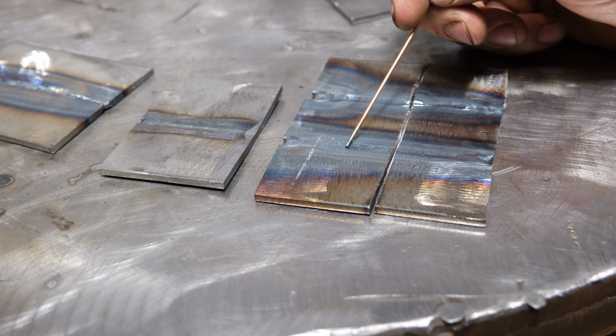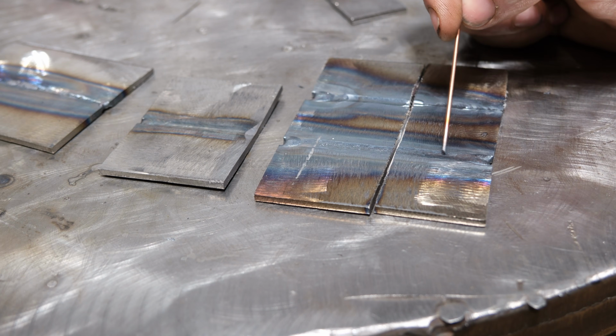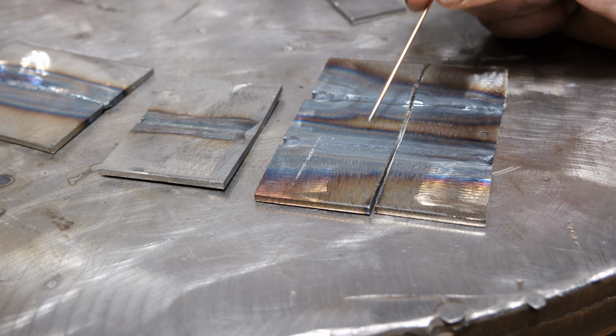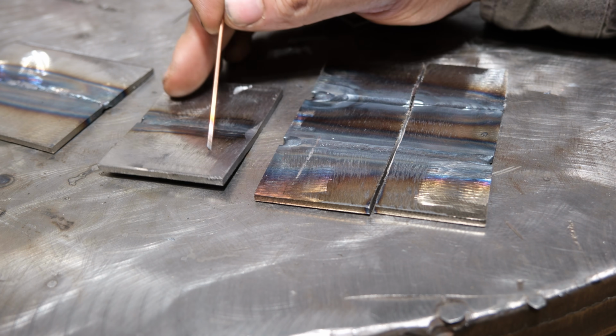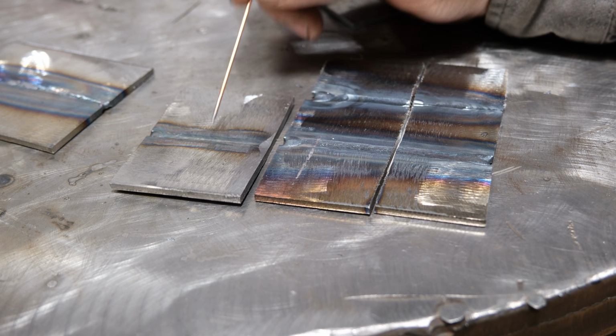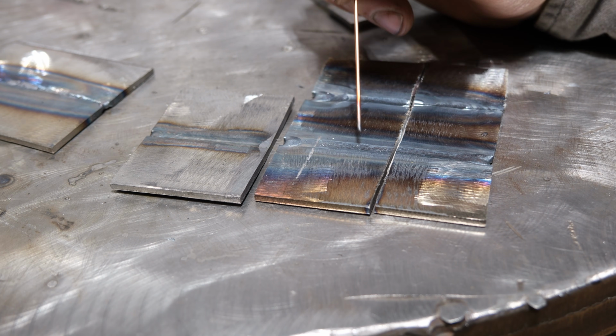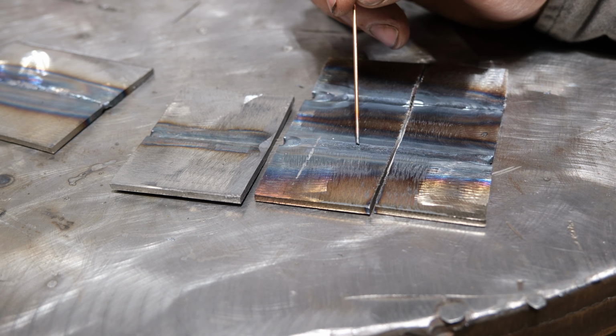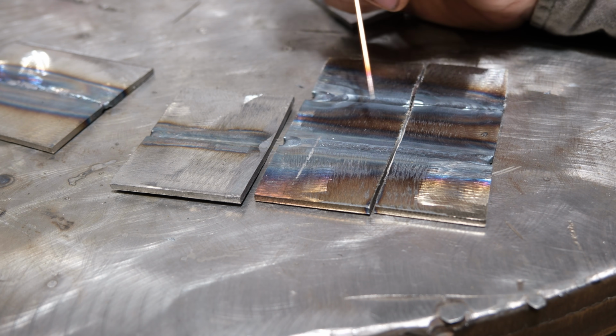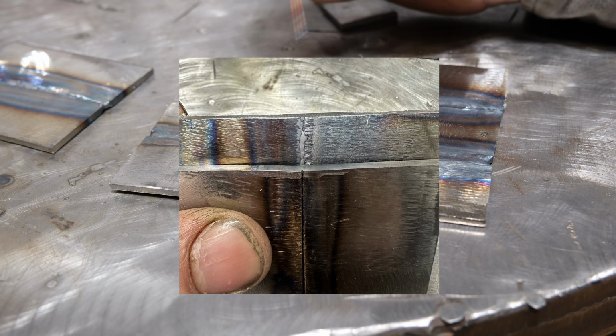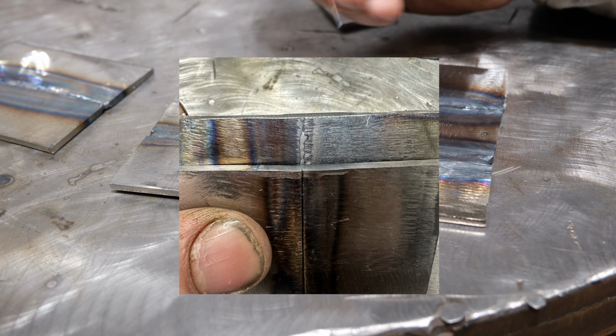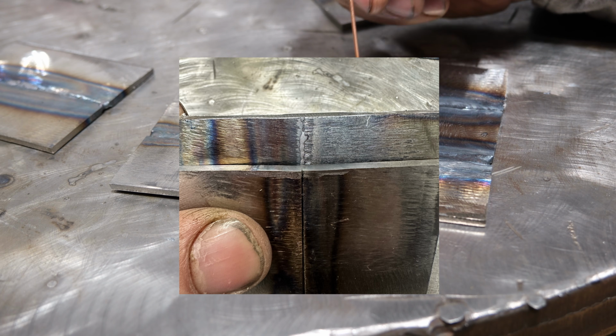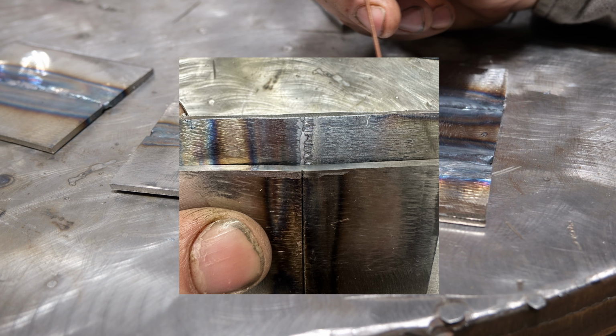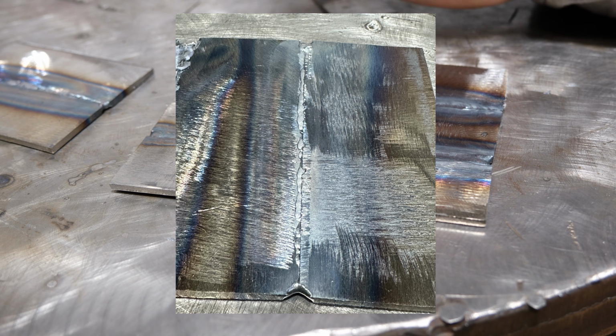So here is that fusion weld that you just saw the arc footage of, and you can tell just by the way this looks how high the heat input was because of my slow travel speed. When you compare it to this other fusion weld, it is a night and day difference. Therefore, the results are also night and day different. And I'll put pictures comparing these two up right now and talk about it. So what we're dealing with is we were able to almost fully weld 1/8 inch material via a fusion weld and produced a very strong weld without filler, simply by slowing down.